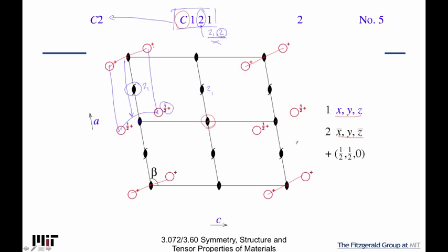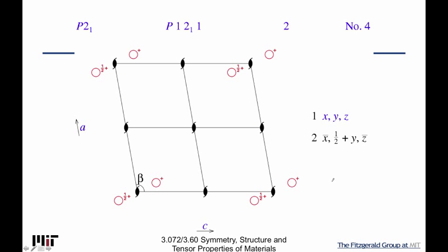We have an additional basis atom from coming up halfway over this twofold axis. From the notation point of view, that's one-half, one-half, zero to get up there. Now with our knowledge of screw axes — just like in the 2D system where once we knew we had a glide system we went back and took lattices compatible with it — we're doing the same thing here. Here's our primitive monoclinic lattice where we've placed a 21 axis in each of these positions.